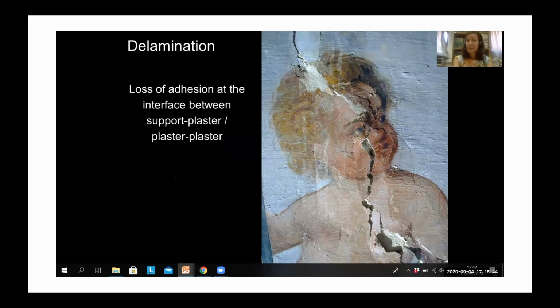So in a delamination, you have indeed loss of adhesion at the interface between either support and plaster, or for instance, plaster and plaster. And so you can see here an example. And what is quite dangerous about it is that when it's highly unstable, such as in this case, for example, you risk basically the total loss of the painting.